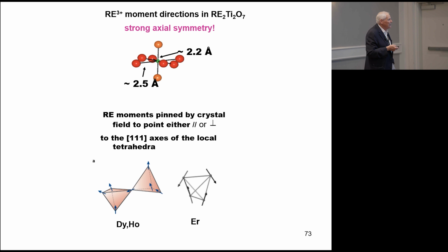Okay, so I just want to finish by making comments about some other features of the pyrochlore oxides, which are remarkable. I just go back to this local symmetry of the rare earth site. It's extremely strong axial symmetry. When you work out the crystal field expansion, the crystal field potential, the axial term, the first term, the so-called B20 term, is extremely large due to this strong axial symmetry.